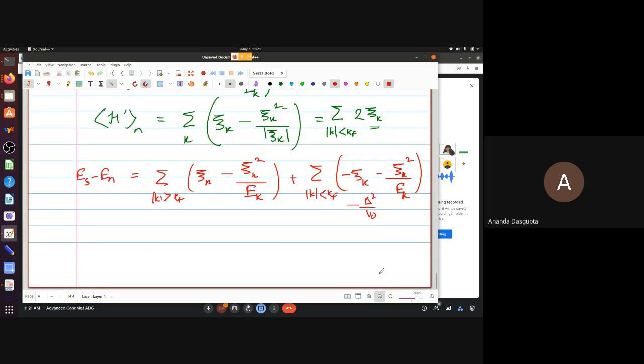Right? So the stabilization in energy because of the formation of this Cooper pairs structure of this superconducting state is given by this quantity, which you can simplify because if you compare this sum and this sum, this is a sum for all momenta above kf of this quantity, and this is for all momenta below kf for this quantity. But our systems are typically symmetrical about the Fermi energy, right? If they're symmetrical about the Fermi energy, then these two sums actually end up being the same, at least within whatever approximation we're using.